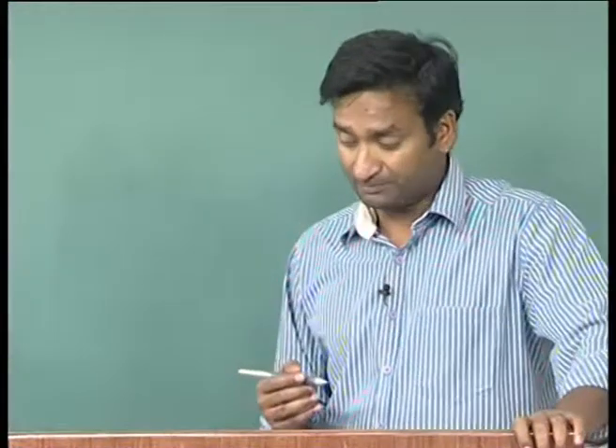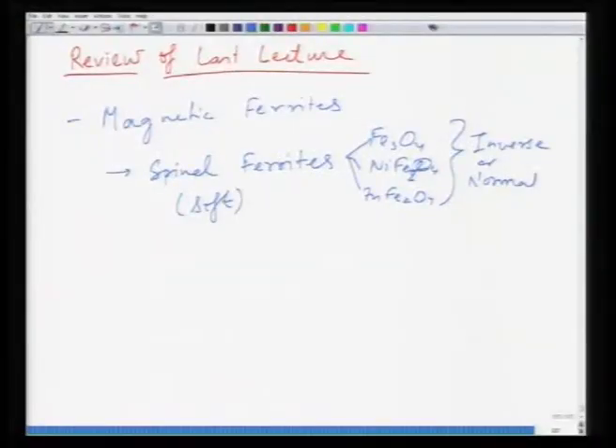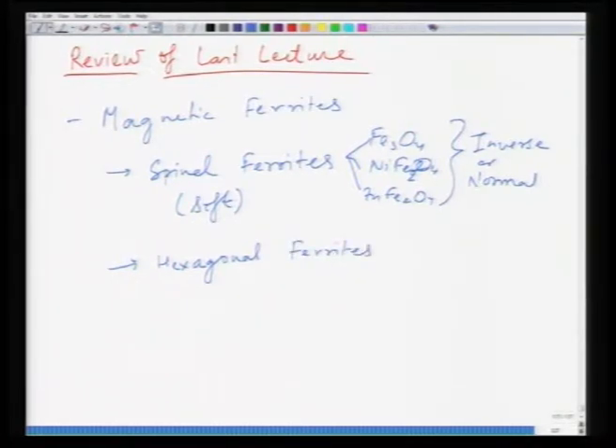As a result, these materials happen to be quite magnetic in nature — they have large magnetic moment and they are soft materials, which means they have a slim hysteresis loop. So they are typically soft ferrites. Then we talked about hexagonal ferrites. In the hexagonal ferrites we were mainly interested in barium ferrite — barium hexaferrite — which is based on the mineral magnetoplumbite, and that is why it is also called as M-type ferrite.